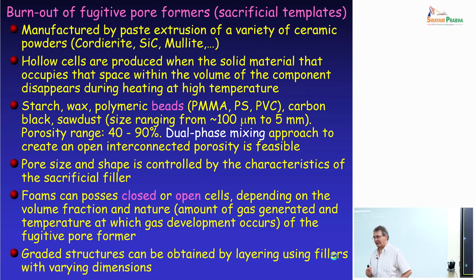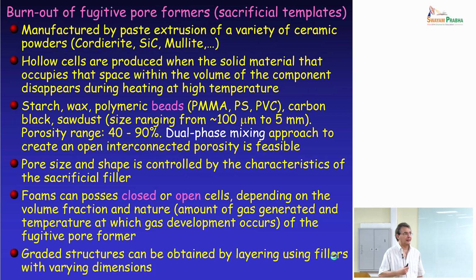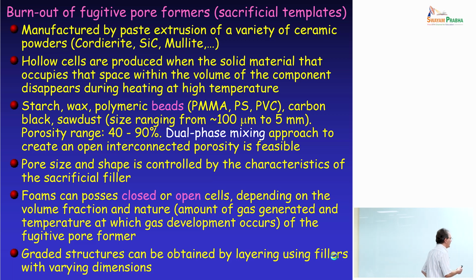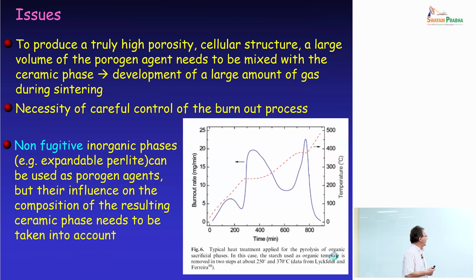Another way of making ceramic foams is to simply use sacrificial templates. In this case, you have some materials that volatilize during processing. You can use sawdust, carbon black, polymeric microbeads, starch, or wax, and in this way generate a wide range of pore shapes. Depending on the volume fraction and nature of the material, you can obtain either closed or open cell structures. And the size of the materials that you use as templates can range widely. This is a list of the materials that have been used.